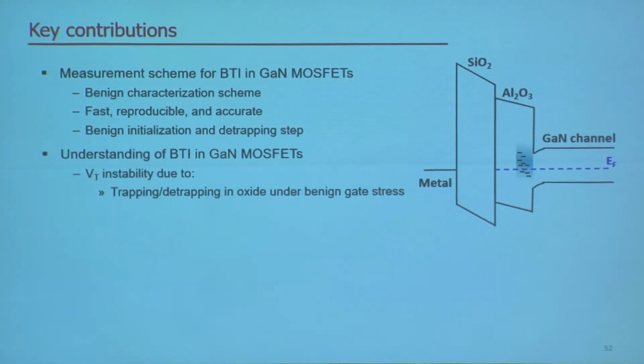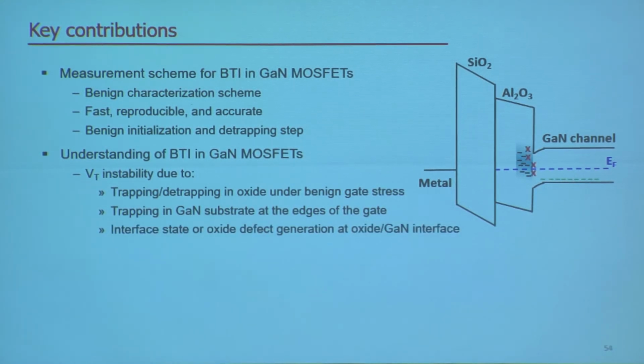Next, we provide understanding of BTI in gallium nitride MOSFETs. The VT instability we have studied is due to three different kinds of phenomena. First, for the benign gate stress, there's this trapping, detrapping symmetry in oxide, as I have explained earlier, that defect band inside the aluminum oxide. And for PBTI, we have this additional positive gate bias, positive VT shift, which is due to the gallium nitride channel trapping at the edges of the gate. And lastly, when we increase the stress voltage to pretty high voltage, harsh stress, there are additional interface state and near interface oxide trap generation.